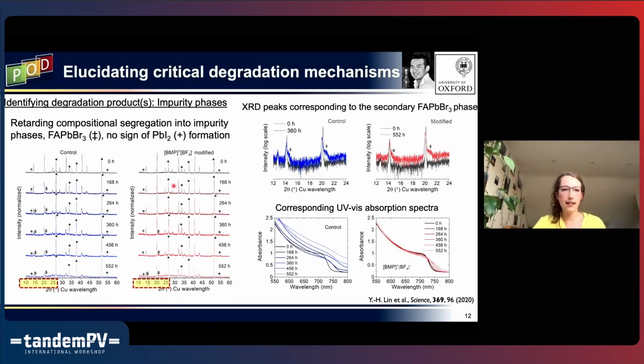So looking at the degradation pathways that this piperidinium salt is helping to suppress, we can look at the XRD pattern as the films are exposed to light for hundreds of hours. One of the things we see is the secondary FAPbBr3 phase growing in, within this 360-hour time frame for just a neat film. But with the ionic additive in there, that phase starts to grow in slightly, but not nearly as early as with the control film. We also see the appearance of this lead iodide peak fairly early on with the control, versus with the piperidinium salt added, it's not growing in.